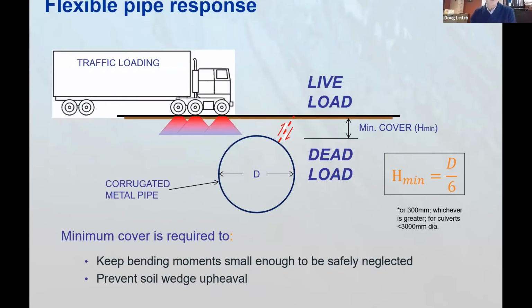A little bit about how the actual response is. If you look at this, the important part of designing any pipe is typically the height of cover, or the distance between the top of the pipe and the load carrying surface, in this case, the roadway that you see here. That particular minimum cover is important because it keeps a bending moment small enough that it doesn't disturb or hurt the pipe at all.